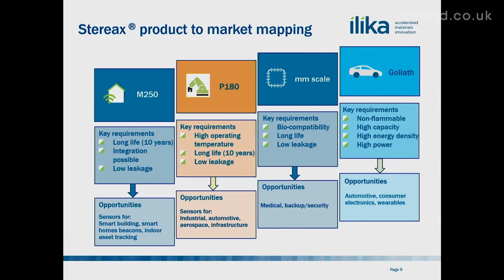Millimeter scale devices are really most useful for medical devices. That's because these are typically implants, and we're going to talk about some of the deployments that we've got there. Clearly, the smaller the footprint, the more useful the battery is, and again, that's a strong differentiator relative to standard coin cells and other lithium-ion cells, because there's a sort of manufacturing limit below which the manufacturing processes aren't really useful when you're trying to encapsulate a liquid electrolyte. But you can take one of these solid devices down to the millimeter scale and implant them very readily. Effectively, you use a microfabrication or a photolithographic process in order to make these millimeter devices.